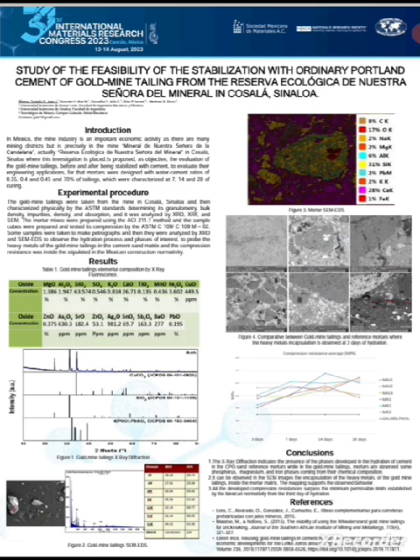So, with that information, the proposed objective is the evaluation of the gold mine tailings before and after being stabilized with cement to evaluate their engineering applications. For that, mortars were designed with water cement ratios of 0.35, 0.40, and 0.45 and 70% of tailings, which were characterized at 7, 14, and 28 days of curing. All of this with the hypothesis that the toxins are going to be trapped in the mortar matrix and reaching the requirements to be considered a material for construction.